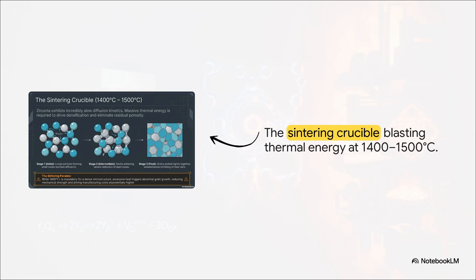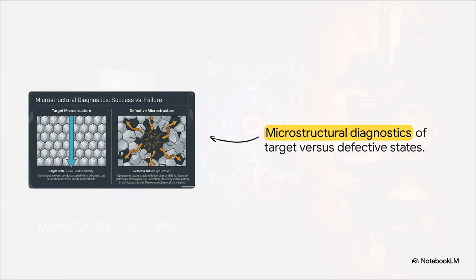While this brutal heat is absolutely mandatory to create a dense microstructure, just a little too much heat triggers abnormal grain growth, and that shatters the mechanical strength and drives manufacturing costs right through the roof. The stakes for getting this right are just absolute. Our target state has to be over 95% relative density. It needs to be this beautiful, continuous matrix that allows pure oxygen conduction while perfectly separating the volatile fuel gases.